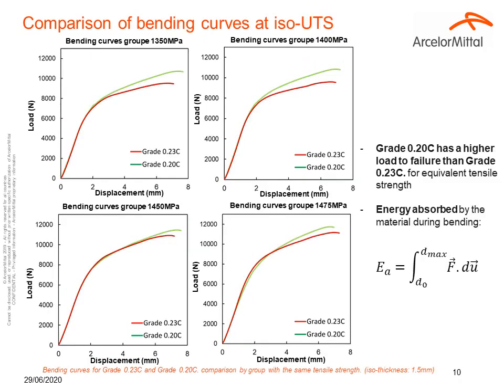In the same way, you have the comparison of bending curves for the four groups and for the same tensile strength in each group. These curves represent the load versus the displacement during a bending test. In all groups, the grade 0.20 has higher load to failure than grade 0.23 for an equivalent tensile strength. Thanks to these bending curves, it's possible to determine another key parameter in crash ductility, which is the energy absorbed by the material during bending.